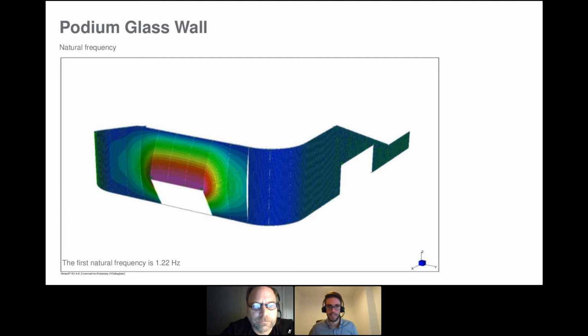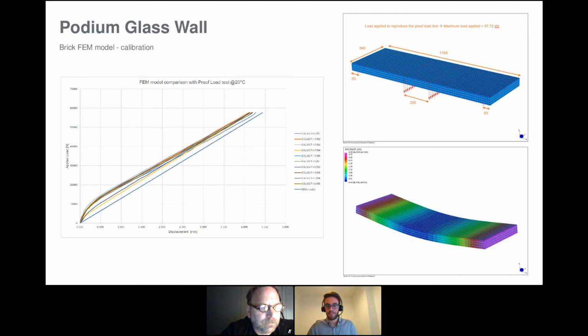What we have to do as well were few brick models for the building department and for the approval authority procedure. And what we had to do as well in Hong Kong is clearly a four point bending test to evaluate the composite action in the buildup. This is mandatory in Hong Kong. So if you want to use effective thickness and therefore composite action in the glass, you must do a four point bending test.